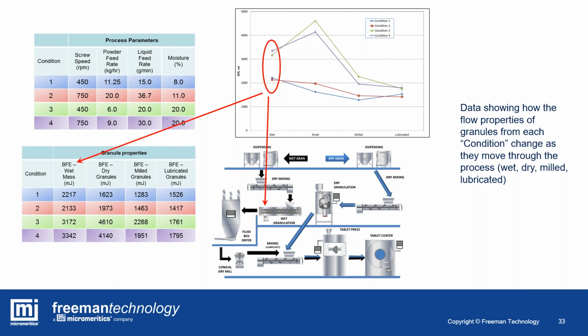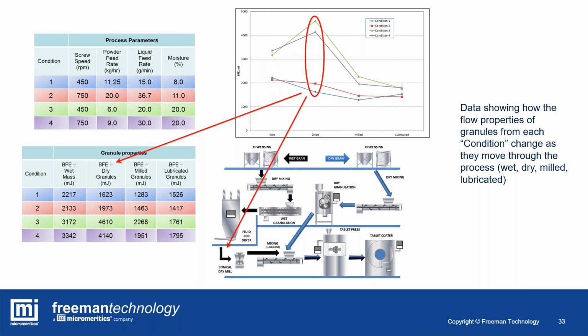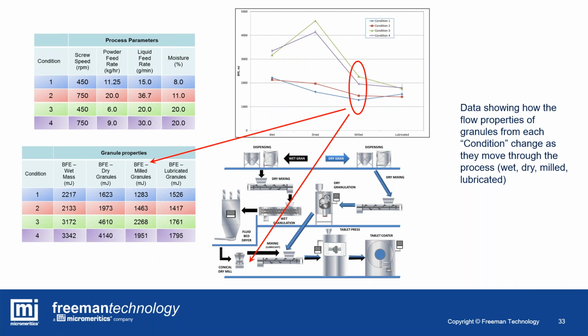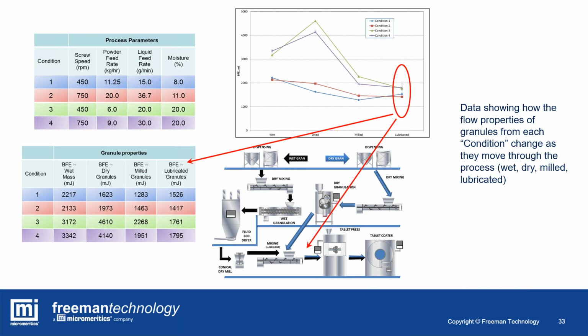If you then take each of those candidates and put them through the dryer, you can now see that you have a change in flow properties. The lower moisture content samples actually reduced in flow energy, probably as a process of some small amounts of attrition and rounding of those granules, which are not so robust, not so hard. The opposite is true for the denser granules, which probably preserve their structure, but in fact become quite stiff systems as the moisture is removed. And then as we go through the milling process, you change the flow properties, of course, you're changing the granules shape and size. And then into the lubrication step, we're adding magnesium stearate here. Again, you change the flow properties of the material. So we can track the attributes of those different conditions right through the manufacturing stages.